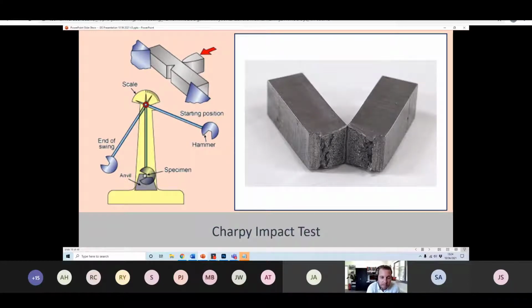In fact, if you want to measure the true toughness of a material, or its fracture energy, or something like that, then it's best to use something like the Charpy impact test. And we indicated early on in our historical overview of mechanical testing that this arrived on the scene in around the early 1900s. And this is a much better way of measuring toughness of materials because it directly measures the energy absorbed during a fracture test, okay? And it's the energy absorbed purely related to the propagation of a crack.